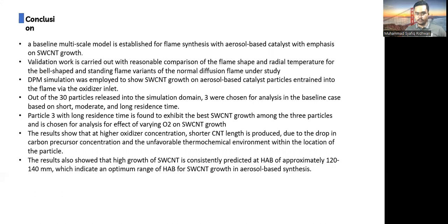The result also showed that the high growth of single wall carbon nanotube is consistently predicted at HAB of approximately 120 millimeter to 140 millimeter HAB, which indicates an optimal range of HAB for single wall carbon nanotube growth in aerosol based synthesis.